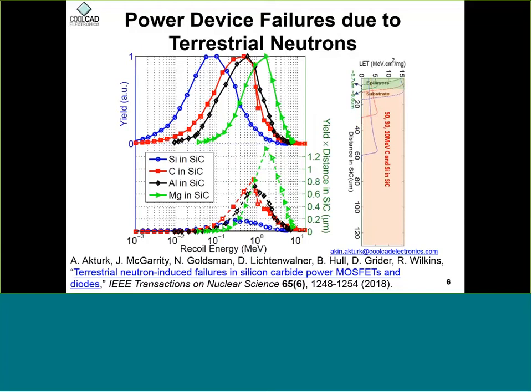Since neutrons are a result of lots of collisions with atmospheric gases and the high energy cosmic rays, they have a spectrum. So the atmospheric neutron radiation energies can go from less than an MeV to up to a GeV, and at high energies you can find fewer neutrons, so you have more of them at lower energy. So this is a spectrum of energies. The knock-ons will also have a spectrum of energies. So that's why you can see at low energies, recoil energies are low, and at high energies, since there are not too many neutrons, your yield is again low. So there's an optimum point.